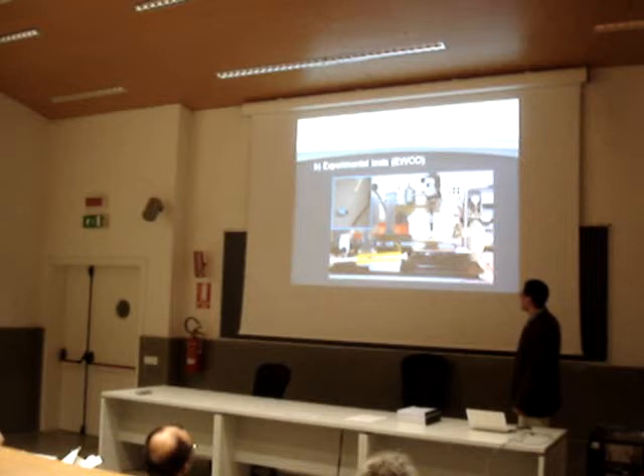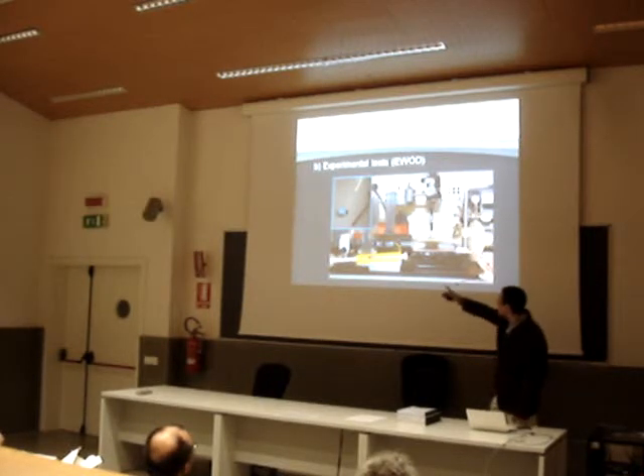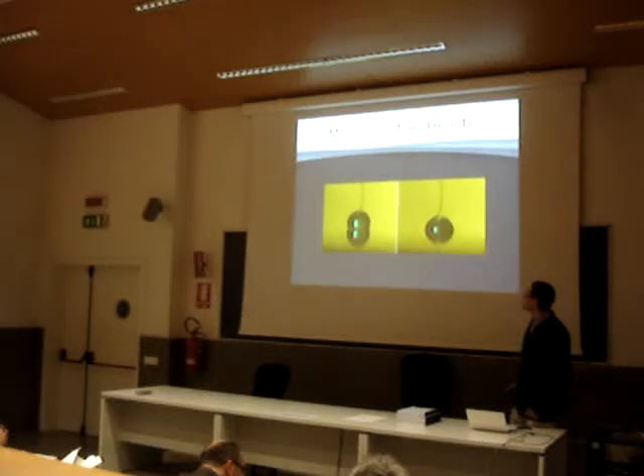And this is the setup I have made with a camera to measure the contact angle of the droplets that I have shown. First, I need to see if the evaporation of the droplet has some effect, just to not be that biased by it. And I can see that after 400 seconds, there's effect. So if I can do the measurements between that period, I have not the effect of the droplet evaporation.